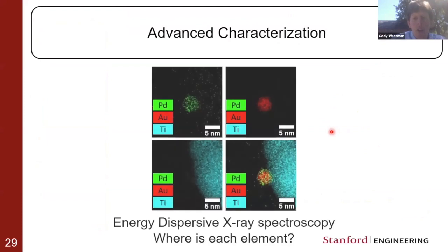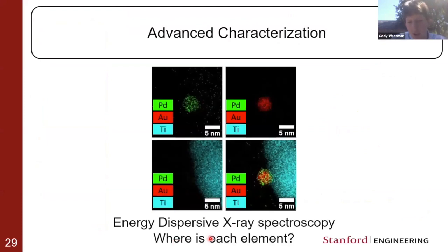Some more advanced characterization techniques that we might be able to do is we can add something called energy dispersive X-ray spectroscopy onto TEM. So if you imagine the TEM images previously, when we add this technique onto TEM, we can start telling where different elements are. So in this upper left image, all of the green dots represent where palladium is. In this image, all of the red dots represent where gold is. And here the teal dots represent where titanium or the support for this catalyst are.